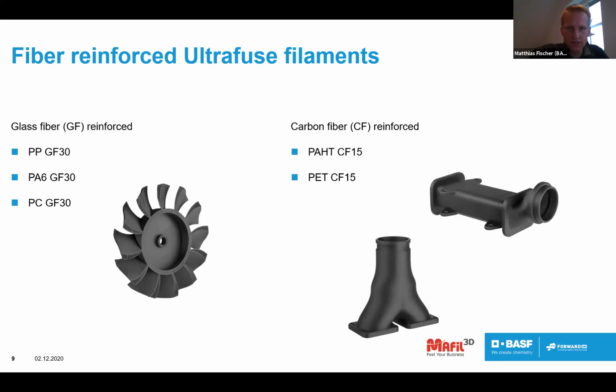Polyamide based is a PAHT CF15, which has an increased temperature stability, but also extremely high stiffness. It's, I would say, the filament with the highest stiffness in our portfolio, with a Young's modulus of about 8,000 megapascal in flat build orientation, which is really very impressive for a filament product in general.